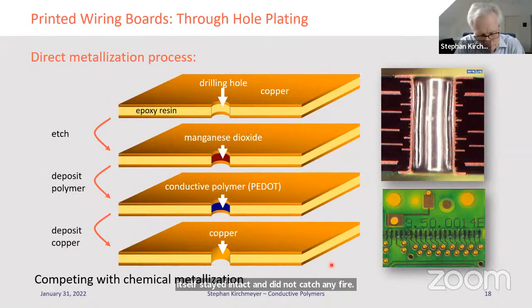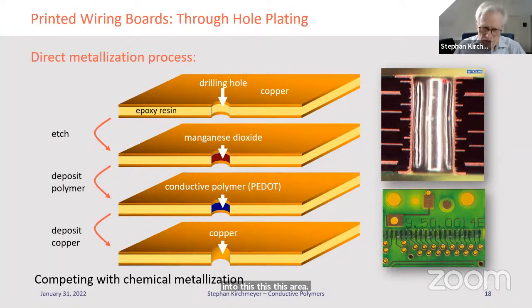The second process I wanted to show you is the metallization of through holes of printed wiring boards. So we are talking about this part here. We have a ring or something which is connected to wiring on the top, the same on the bottom, and we want to make a metallization through this. We have basically two options. One is we take palladium catalysts and impregnate it into the hole and use a chemical bath. And this chemical bath then deposits copper on top of the palladium catalyst, and then slowly a copper film grows on top of this. This is one way. This was the established way before the PEDOT got into this area, and it worked well so far. There are two problems.